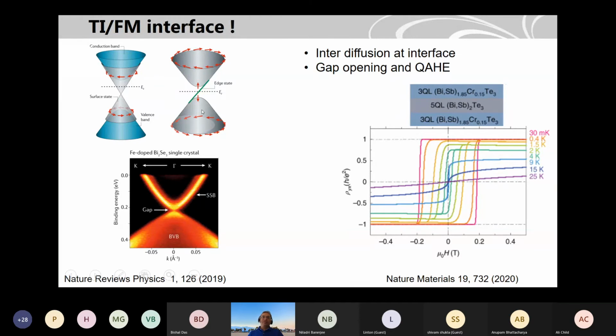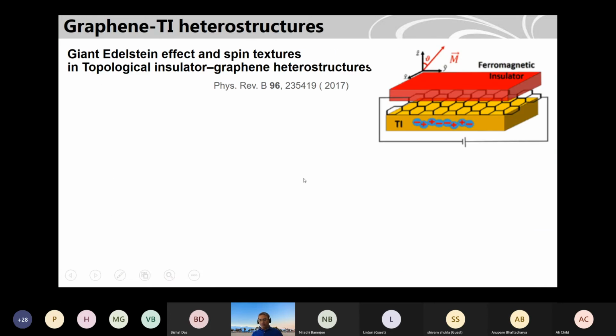First it was observed in chromium doped topological insulators. And because it was limited to low temperature, people tried these proximity effects. So people have different layers with chromium doping here and with just bismuth antimony telluride. It's a multilayer structure. So this is the quantum anomalous Hall effect that you see. It's well quantized, but it's at very low temperature. But it is happening with proximity now.